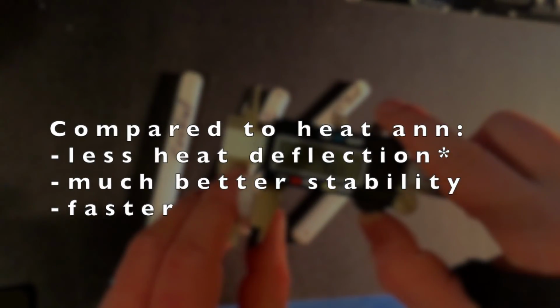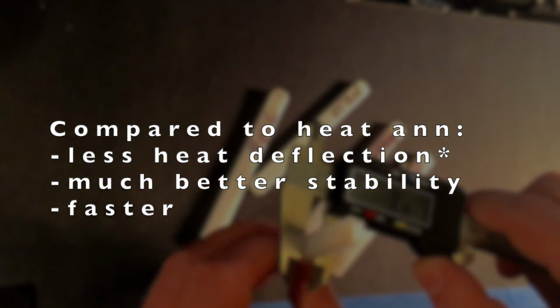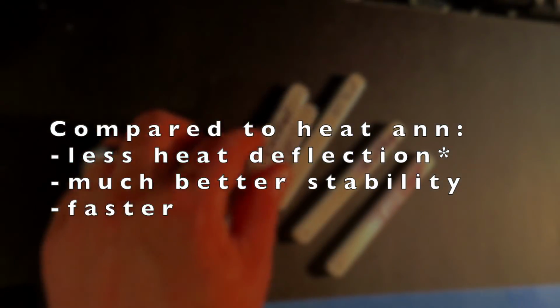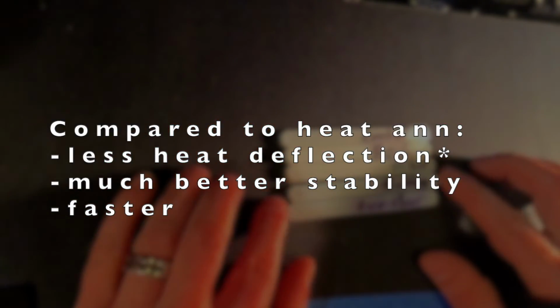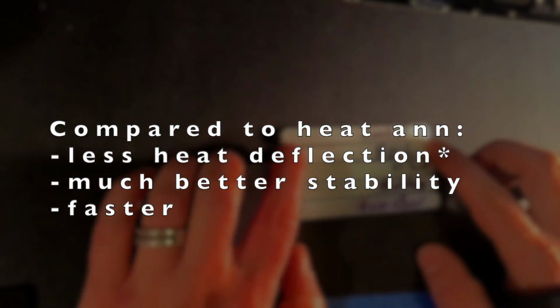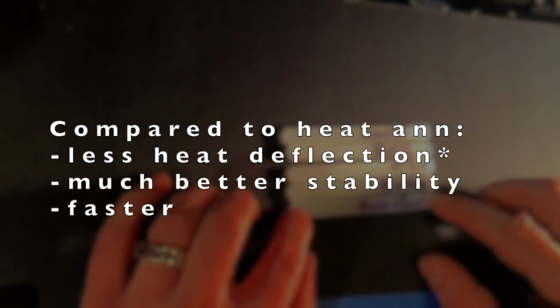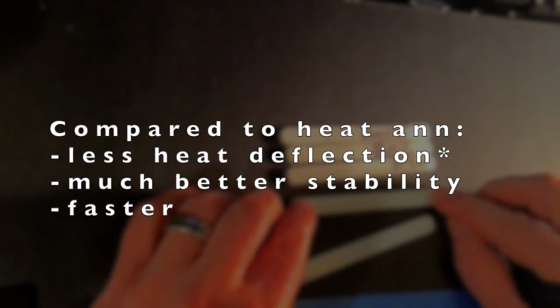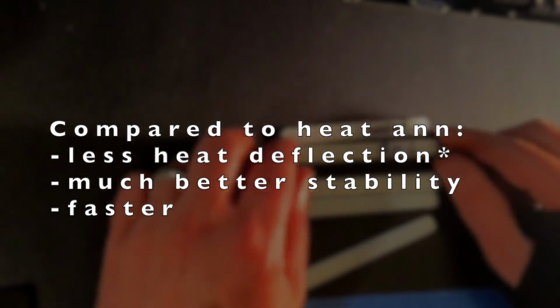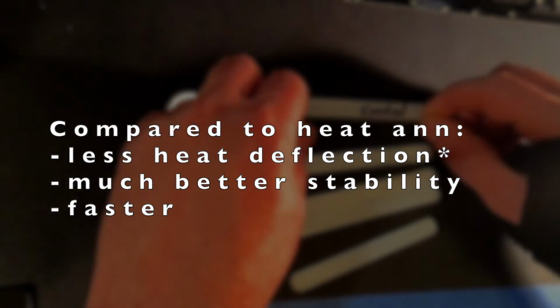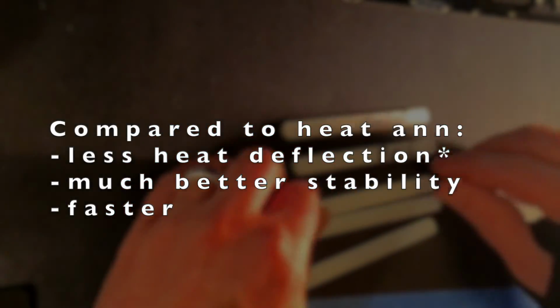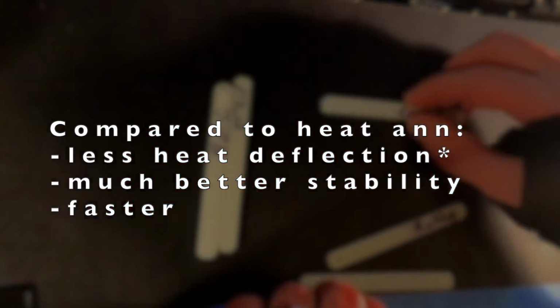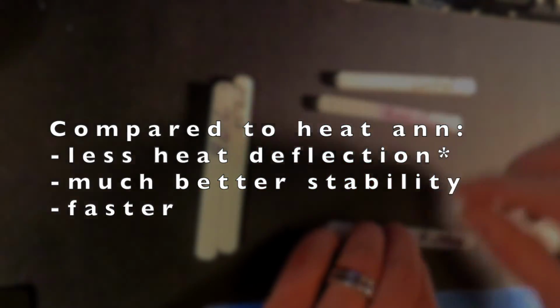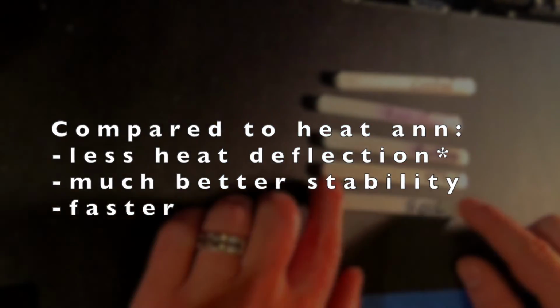And in terms of comparing it to heat annealing, it definitely has less heat deflection, but it's much, much, much better than raw PLA. But it does have much better dimensional stability, which is very important because who cares if your parts hold up to the heat if they're all distorted, and it's a lot faster. I mean, we're talking 5, 7, 10 minutes versus cooking something for half hour, 45 minutes, an hour on a build plate or something like that.